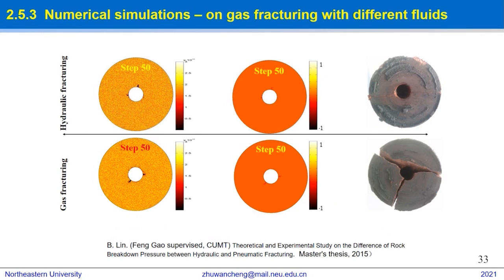This slide shows the numerical simulation results of fracturing with different fluids. Two fractures are induced by hydraulic fracturing, while three fractures are induced by gas fracturing. We can see that the numerical simulations compare well with the experimental observation. The crack distribution caused by gas fracturing is more complicated.